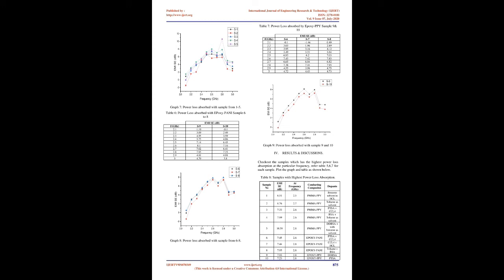Power loss absorbed with samples. To get the reading of power absorbed by the samples, subtract the value of the EMI in dB which we got at frequencies of 2.1 GHz to 3 GHz with the sample inside the waveguide, shown in tables 2, 3, 4, from the output value in dB which we got at frequencies of 2.1 GHz to 3 GHz without a sample inside the waveguide, that is, the empty waveguide shown in table 1. Follow the same procedure with every sample from 2.1 to 3 GHz. Note down the power loss absorbed in dB by each sample at a particular frequency.